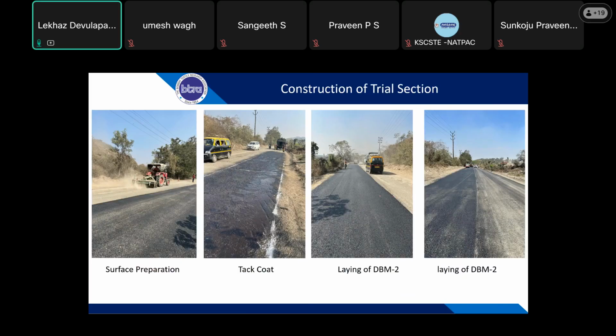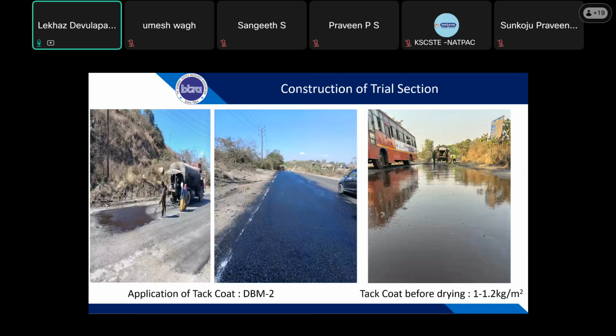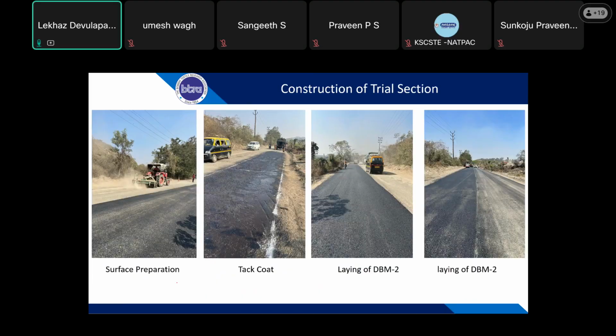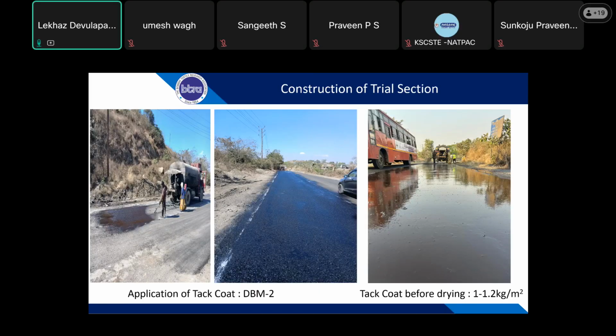We made it in two patches, like a 3.5 meter width, because we want to allow the traffic to move on one side. So the 3.5 meter section was done at one side, and the traffic is left for the other direction. Similarly, the other side also DBM has been laid in that way. Once the DBM has been laid, we again applied a tack coat on top of this.